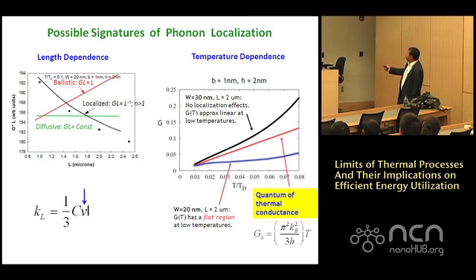The other effect is the temperature dependence. This is conductance versus temperature. If it's purely classical heat conduction, in the sense that you have T-cube behavior for the heat capacity and propagation of all the modes, you will see something like this. You'll see a little bit of linear, and then increasing as more and more modes get excited. If you have localization, you will see a region which is flat, where you can excite the modes, but they won't propagate. And at least my theoretical colleagues predict it's going to be lower than the quantum of thermal conductance.